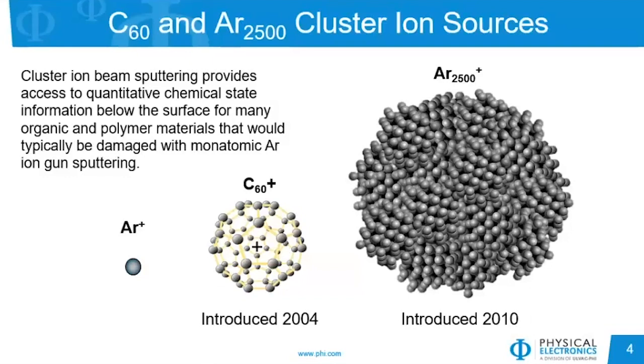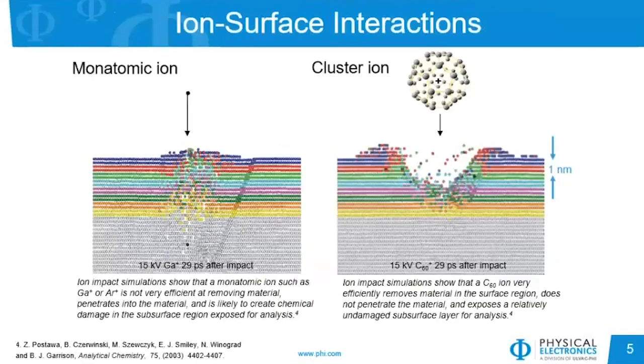And with the cluster sources, it does open up a wider variety of materials beyond those with monoatomic argon. And to help us understand why these cluster sources are more useful to us, we can see here simulations of the impact of either a monoatomic ion or a cluster ion on a surface. What you will see on the left is that monoatomic ions tend to penetrate deep into the material, and they create a lot of damage within the material and actually are not that effective at removing material. However, the cluster ions tend to be more sensitive to the near surface regions, creating a thinner damage layer and also providing a more representative surface as we go deeper into the material.